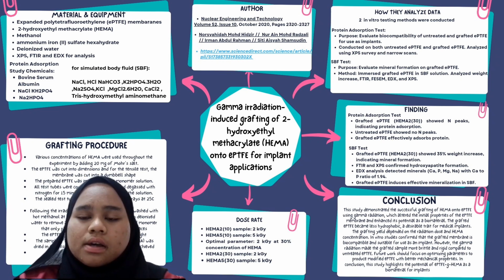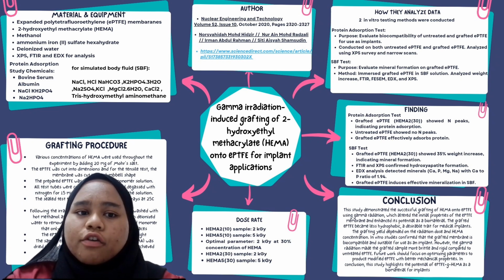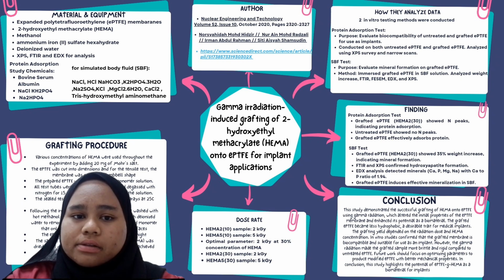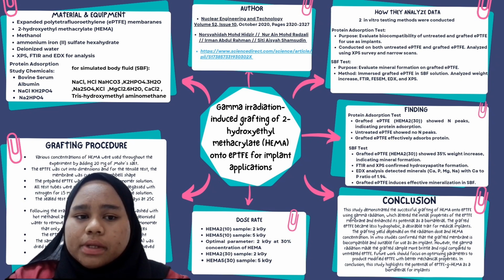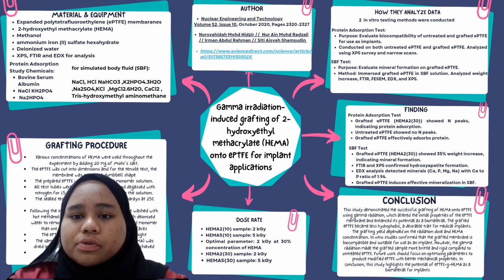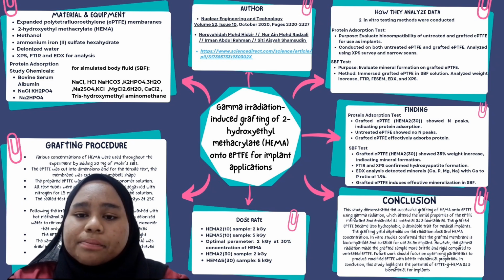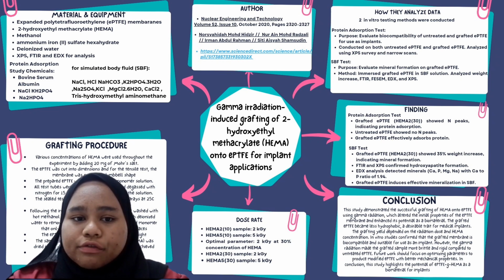So the result of this test is, for the protein adsorption test, grafted ePTFE HEMA 2 30 samples show N peaks, indicating protein adsorption, while untreated ePTFE show no N peaks. So this means grafted ePTFE effectively adsorbs proteins, which was indicated by the presence of N peaks in XPS compared to untreated ePTFE. For the SBF test, grafted ePTFE HEMA 2 30 samples show a 35% weight increase, indicating mineral formation.